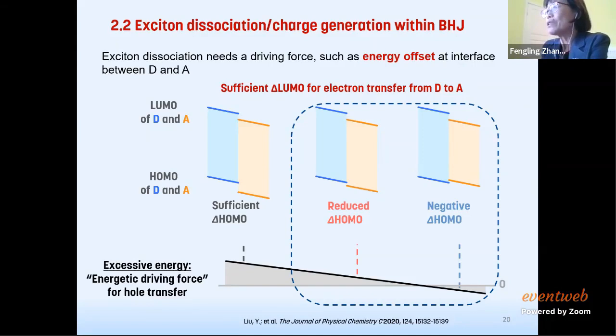So here also I show 3 different situations. When we work with the fullerene acceptors, because fullerene is quite a large band gap material, in most combinations, they have enough energy offset to drive the exciton dissociation. But the non-fullerene acceptors are attractive because they are small band gap materials that absorb more photons, and also they can modify the HOMO and LUMO levels to match the donor. So they try to minimize the voltage loss, meanwhile collecting as many photons as possible to generate photocurrent. So that's the reason they are very efficient, because they can optimize both current and voltage simultaneously. However, there are still some limitations.